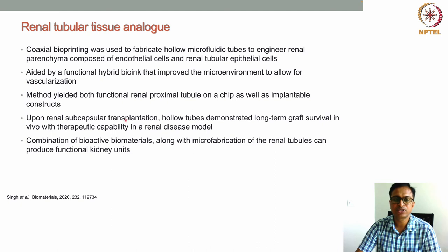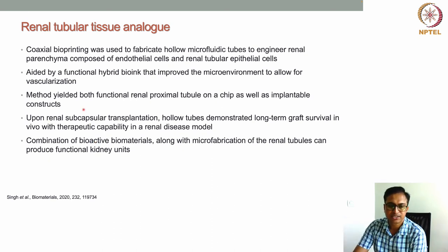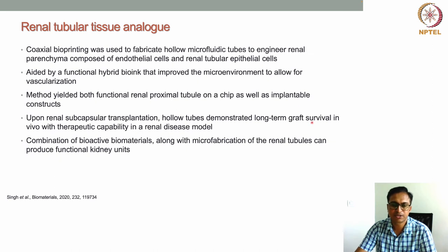In this case, their method yielded both a functional renal proximal tubule on a chip as well as implantable constructs. So basically they have shown both tubule on a chip and also an implantable construct. They performed renal subcapsular transplantation of these hollow tubes, which demonstrated long-term graft survival in vivo with therapeutic capability in a renal disease model. Actually, they created a renal disease model and implanted these tubule structures, and long-term graft survival was seen. So combining bioactive materials with microfabrication of renal tubules, functional kidney tissues can be produced.